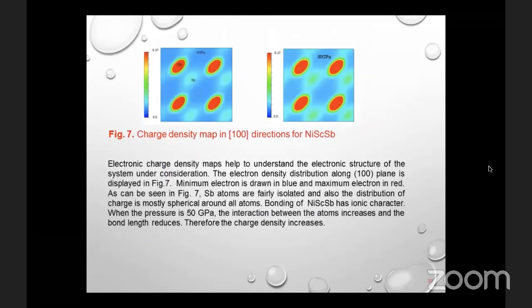We have analyzed the valence electron charge density, and charge density plots of this compound along the 100 plane are given in figure 7 under zero pressure. Minimum electron is drawn in blue color and maximum electron in red color. If you see in this figure, antimony atoms are fairly isolated, and also distribution of the charge is mostly spherical around all atoms. Bonding of this compound has ionic character. When the pressure is increased to 50 GPa, the interaction between the atoms increases and the bond length reduces. Therefore, the charge density increases.